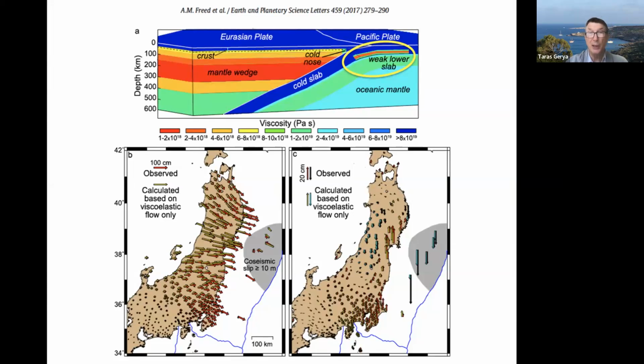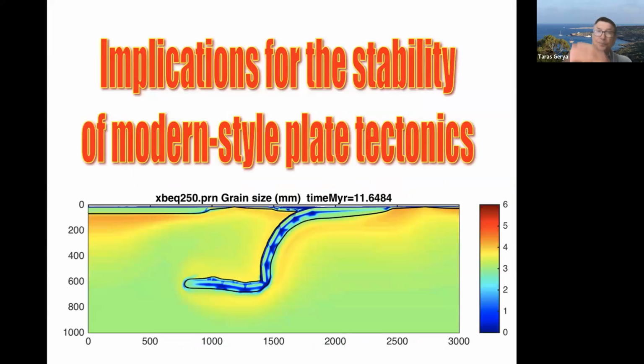It was a very good idea to involve Thorsten, because he also found these segmented seismic velocity anomalies in the Japan slab, which finally convinced us and reviewers that this is an existing phenomenon of slab segmentation. So as soon as we were convinced that this process has a good relationship with reality, which means that slabs, or at least some of them, are indeed segmented when they subduct, we started to think about the implication of this process for the stability of modern style subduction and plate tectonics.